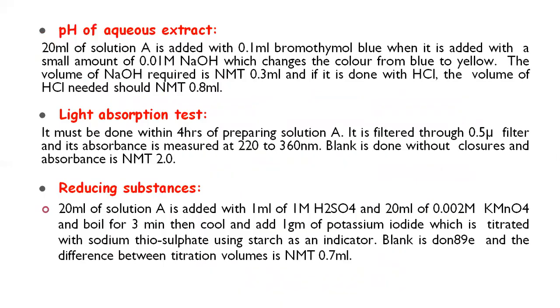pH of aqueous extract. 20 ml of solution A is added with 0.1 ml bromothymol blue. When it is added with a small amount of 0.01 molar NaOH, the color changes from blue to yellow. The volume of NaOH required is not more than 0.3 ml, and if it is done with HCl, the volume of HCl needed should not be more than 0.8 ml.